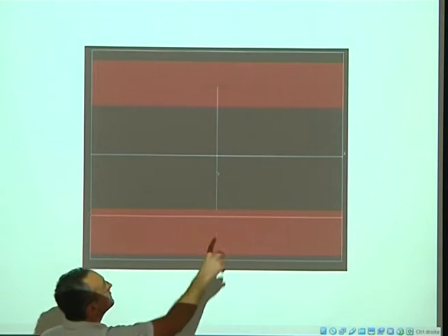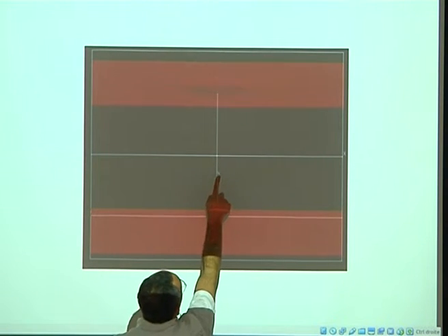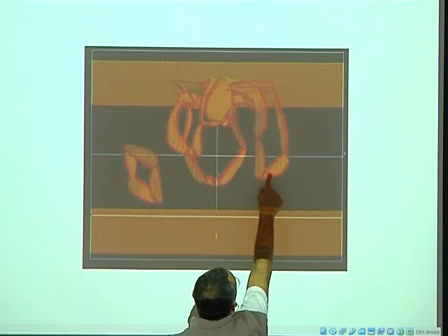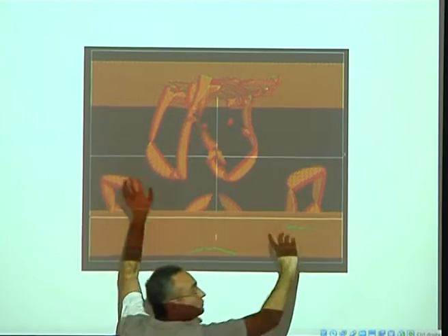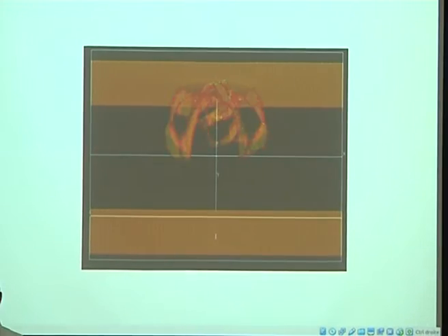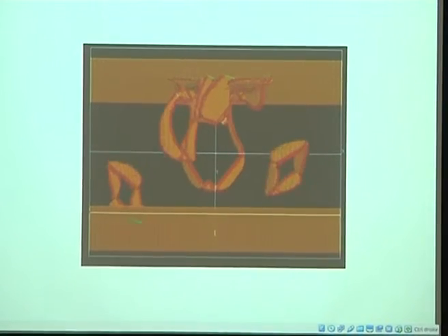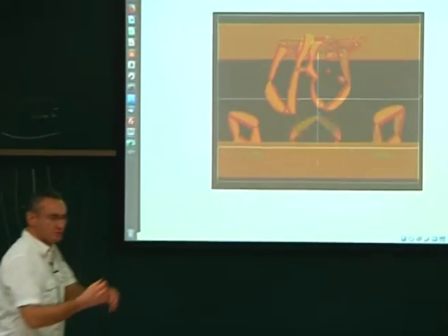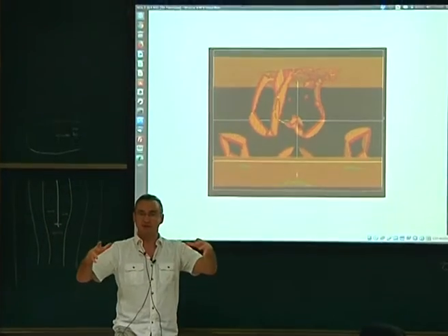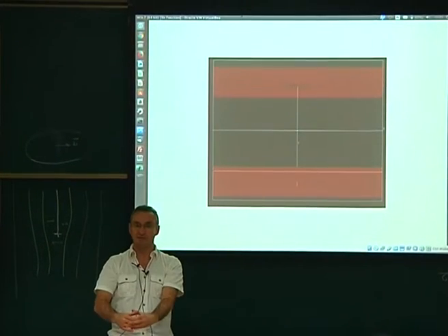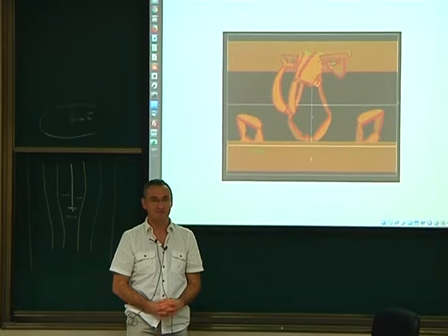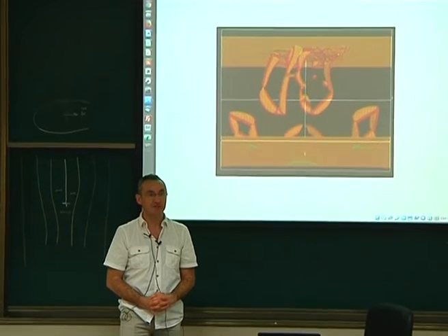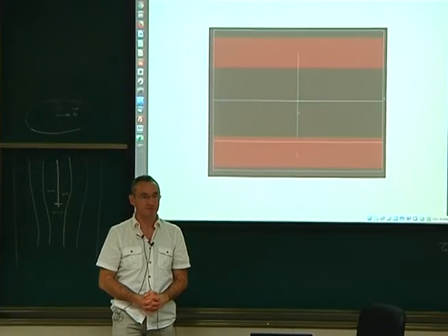You can see that 3 loops come out from that. You can see a first loop which is coming here, a second one here, and the third one on the back. Those two were the two which were interacting before. Okay? Those are called prismatic loops. You see that it's not a loop as we are used to. Usually the loops are supposed to expand. Here they do not expand, they glide. What are these loops? Do you have any idea of what kind of loops these are? Prismatic loops, did you hear about prismatic loops before?